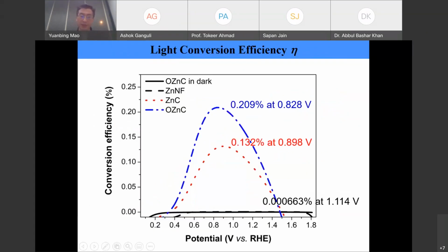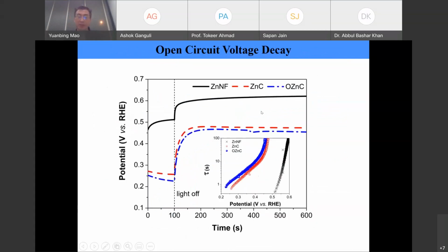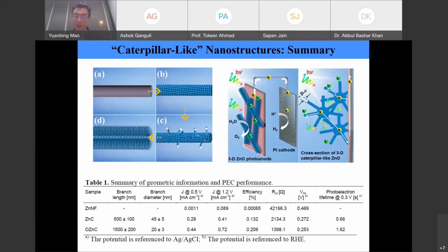And then we also look at the conversion efficiency again. The optimized zinc oxide caterpillars show the highest performance, and this number is not as high as the one we showed before, but it's high enough. We also did something similar for the open circuit voltage decay, and the zinc oxide caterpillars show the best performance. To summarize, this is how the charge carriers move to the substrate in this type of connected nanostructures. And one important thing, as I showed you before, is the conversion efficiency, and clearly we can see the difference between these different types of samples.